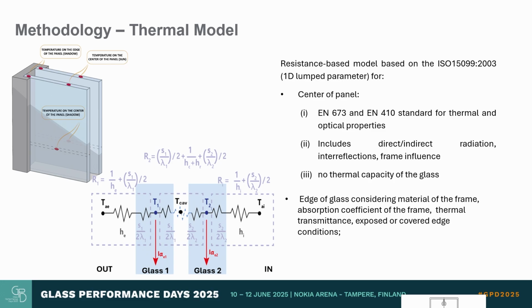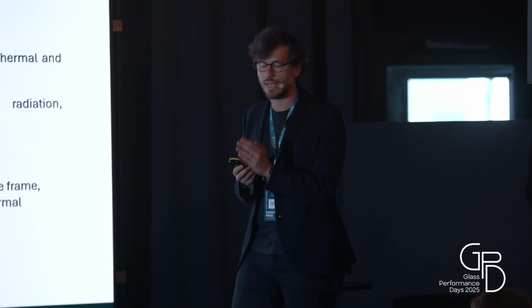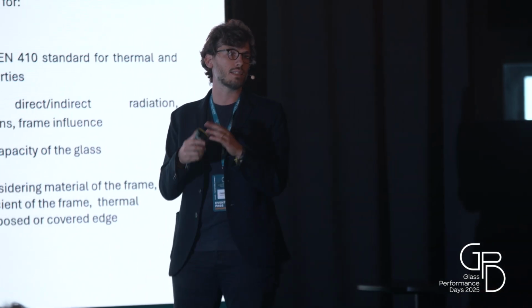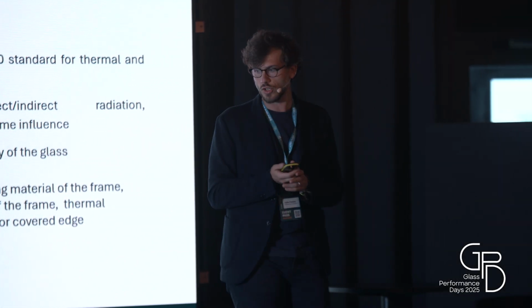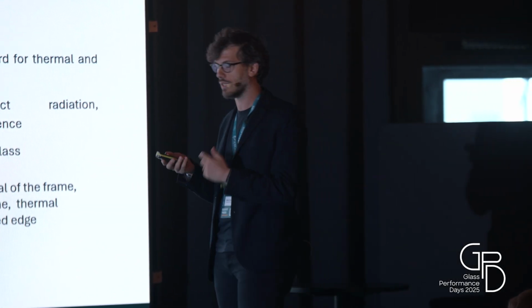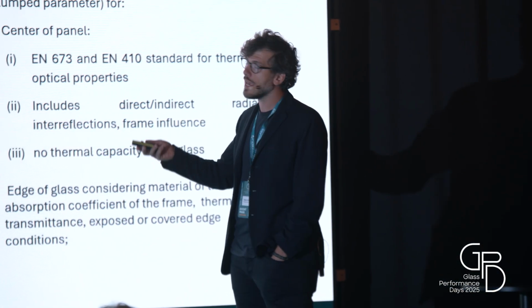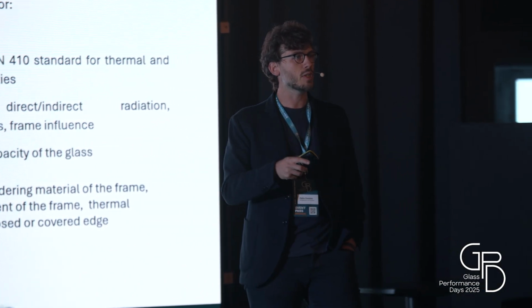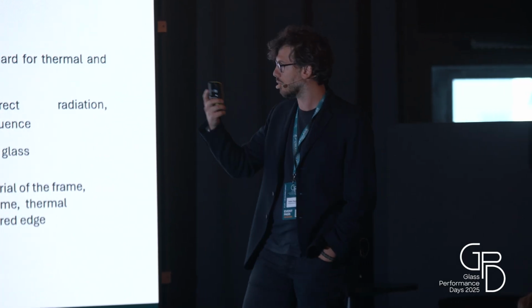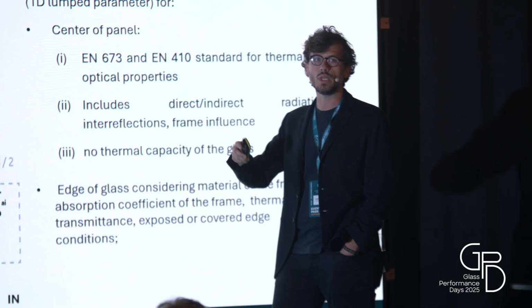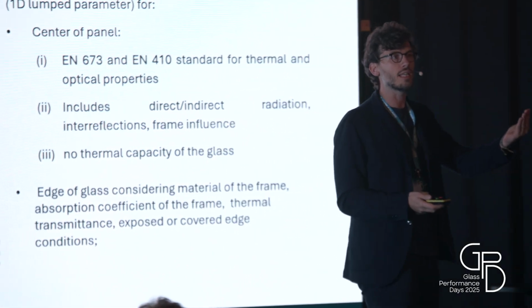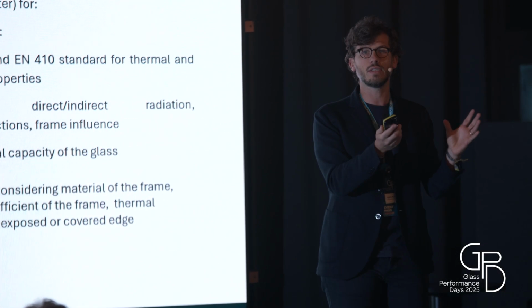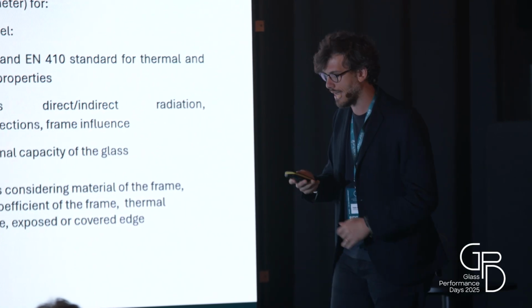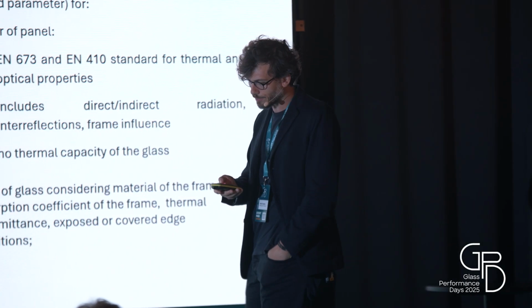For the edge of the glass, we consider different models that account for different frame materials and especially the condition of the edge, whether that's exposed or not, and whether the frame is thermally broken or not, and whether it's window or curtain wall. So we developed different models for that. And then at the end, we consider the delta T, so the temperature difference that might induce thermal shock within one layer, as the worst combination between the irradiated and non-irradiated center area of the panel and the irradiated and non-irradiated edge of the glass.